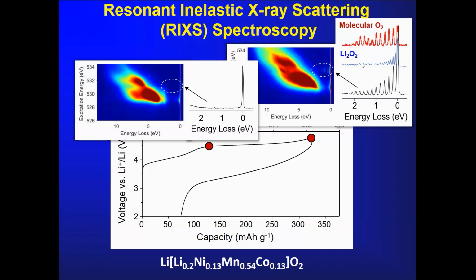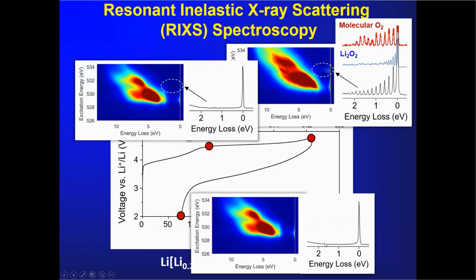Just for interest for those involved in this, this is a spectrum for lithium peroxide, with obviously peroxide ions, and you see it doesn't match the spectrum that we observe in our cathode material. Again, if you notice here in the material before the plateau, before the oxygen plateau, there is no evidence of this vibrational spectrum, no feature here. And then if we look at the end of discharge again, we see that these features have gone. Here's the expanded region, and we're back to something that looks very similar to the pristine spectrum.